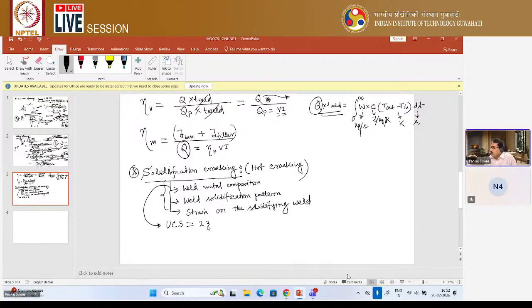You can write this in the form of, generally in case of submerged arc welding, there was a study, because in submerged arc welding, solidification cracking is very frequently observed. That's why there was a study on this, and there this UCS was established. You can write it as 230C plus 190 into sulfur S, based on this weld metal composition, plus 75P plus 45 Nb, all are compositions in the weld metal, minus 12.3 silicon, minus 5.4 manganese, minus 1. Based on this equation, this UCS, units of cracking susceptibility, is generally raised.